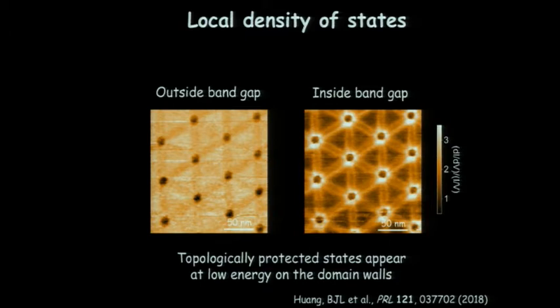But you might expect a similar effect for graphene on graphene, right? Yeah, I think it's definitely possible. But you can map the relaxation of the lattice. Right, but there's not a reason for the lattice to stretch here, because it lacks more AB than AA. But that's still a lattice constant that's the same, right? So there should only be stretching in certain areas. This whole region should be just the normal graphene lattice constant. Yeah, but there are calculations. I know, I'm sure you're aware. So have you tried to map to see? Yeah, we tried it and we saw nothing. Okay, so that is inconclusive, right? It could be that it's too small to measure. It could be lots of reasons.